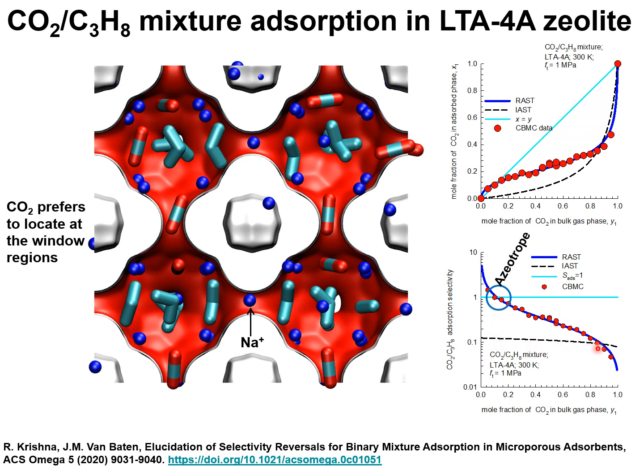The IAST fails to anticipate selectivity reversals because one of the important assumptions of the IAST is that the guest adsorbates are homogeneously distributed within the pore landscape, and the competition between the guest molecules does not depend on the composition of the bulk gas mixture.